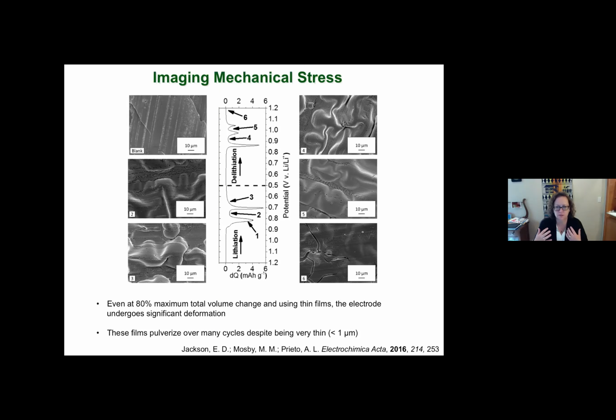So the volume expansion is significant. You can see there are definitely some defects on the surface where the buckling is getting pinned. And then by the time you get to 0.6, where you've completely delithiated, most of that mechanical stress has dissipated, but you see that there are some cracks that remain.